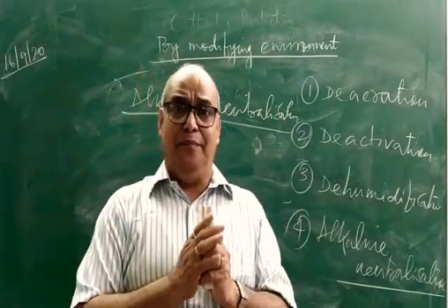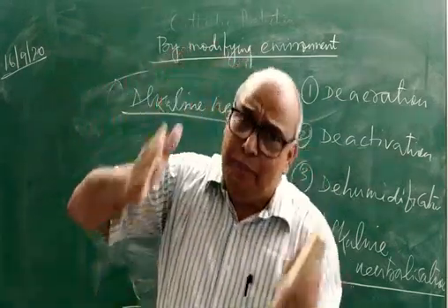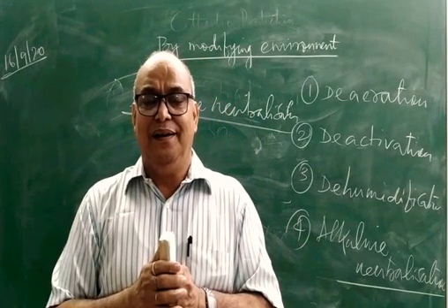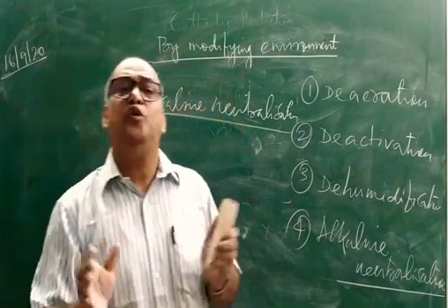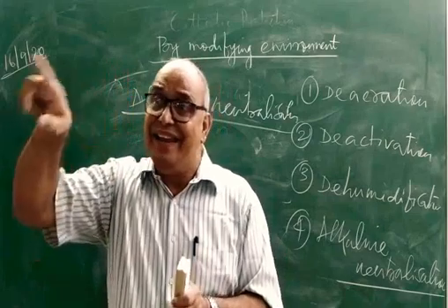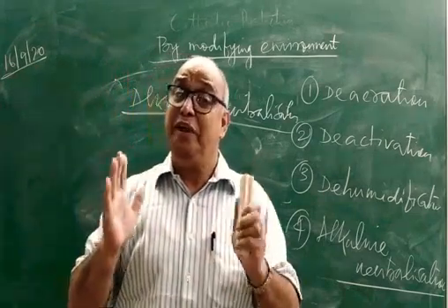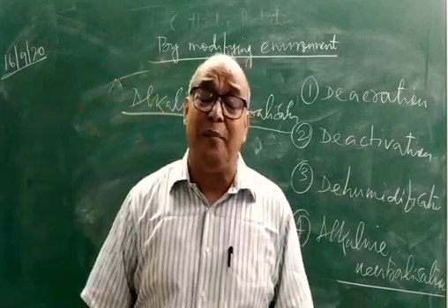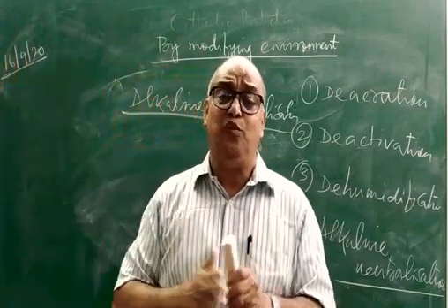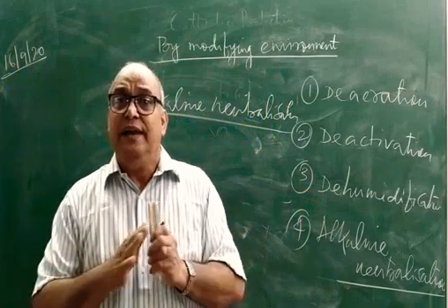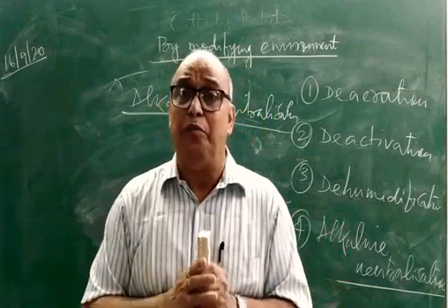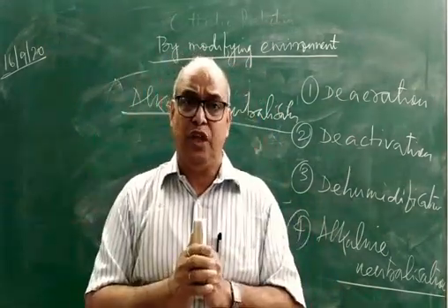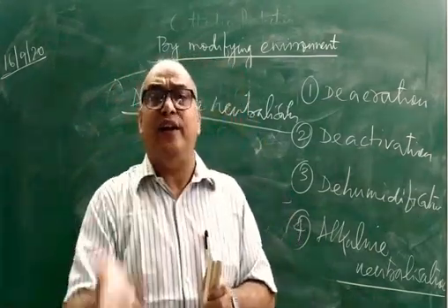So if we can nullify or reduce the acidity of the environment and bring it back to almost neutral level, automatically the rate of corrosion can be controlled. How can we do that? A calculated amount of ammonia or sodium hydroxide, applied in an area in the form of spray, but we have to be very alert. We have to take a calculated amount, otherwise if you take an excess amount of base, your environment will become basic. Then another form of mechanism will be followed, and that is why we have to take a calculated amount of ammonia or sodium hydroxide, so that your environment will become neutral. As a result, the rate of corrosion will be controlled. This process, alkaline neutralization, is extensively used to control corrosion in refinery equipment.